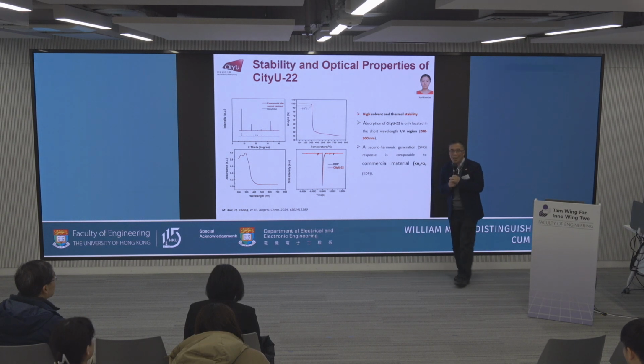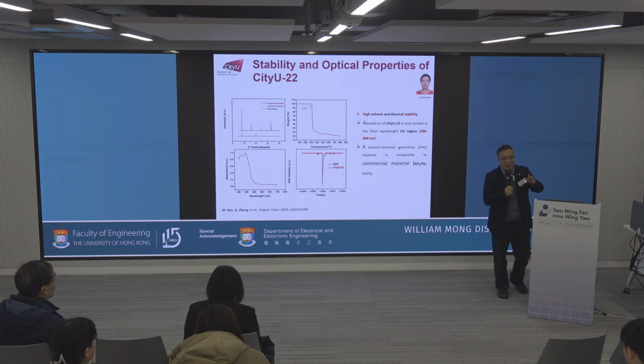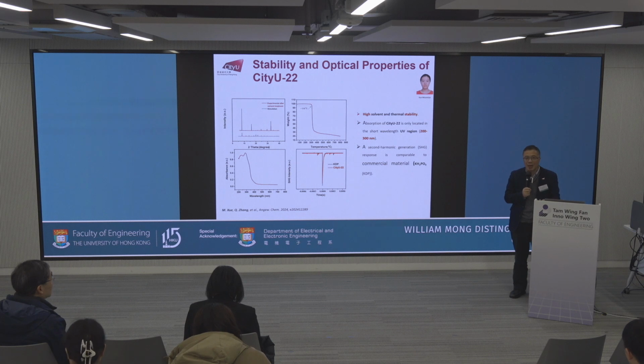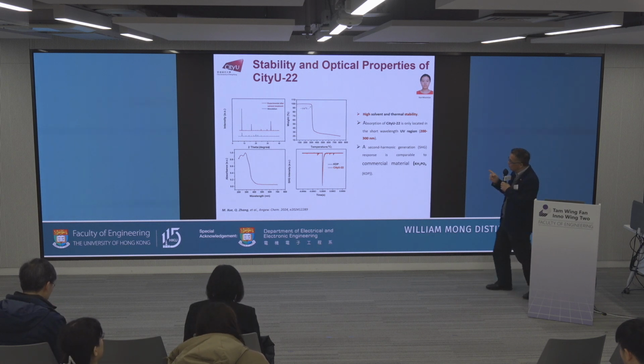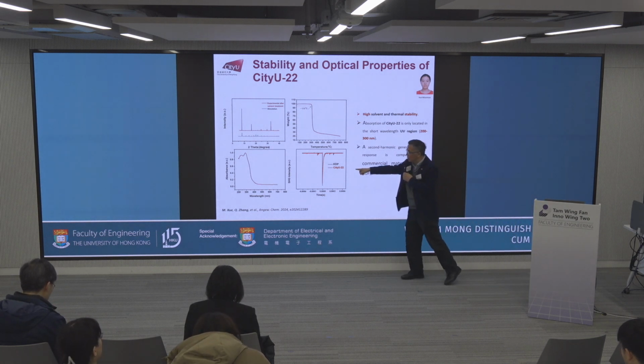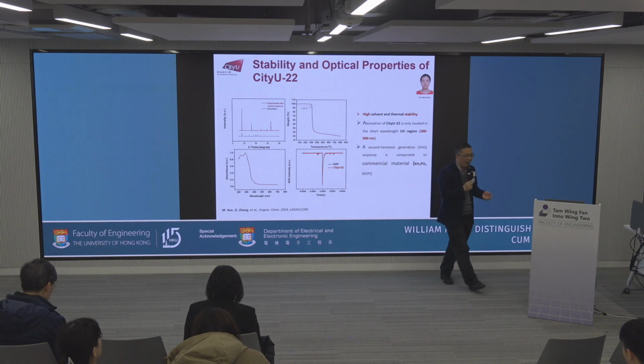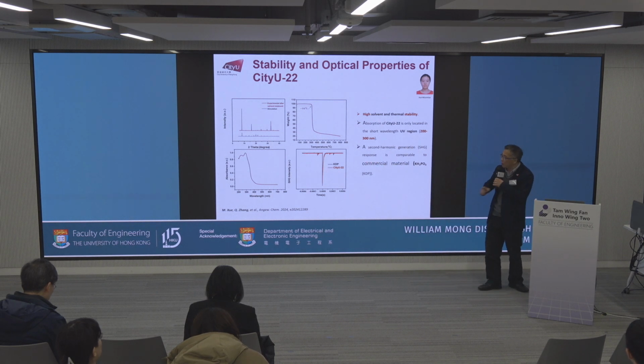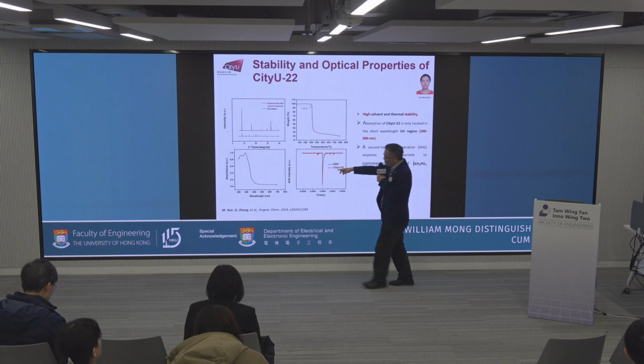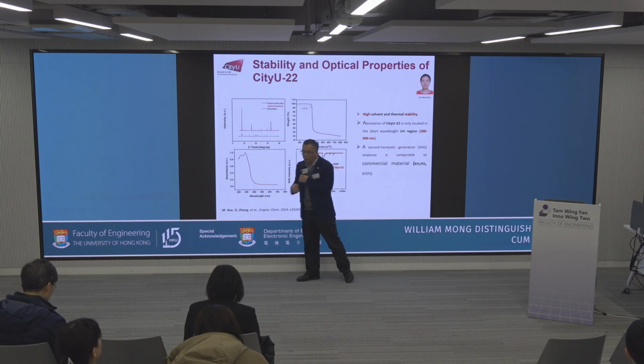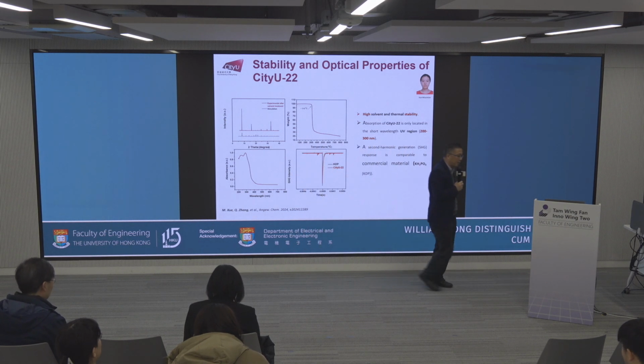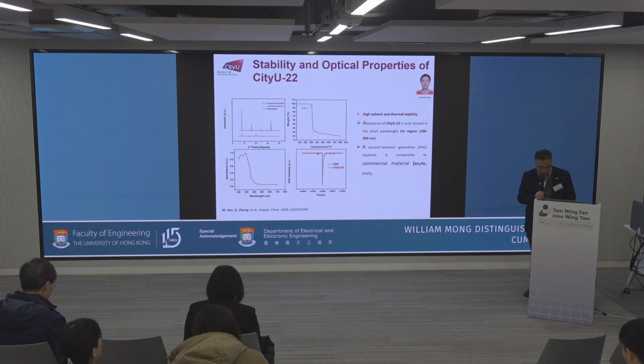But one thing I have to point out is that KDP is very sensitive to moisture, because KDP is an inorganic salt. So in high moisture systems, KDP will have big trouble. So to my understanding, this CityU-22 can replace KDP in high humidity systems. Especially, for example, you can look at our absorption in the UV. Okay, so we can replace ADP or KDP for some applications.